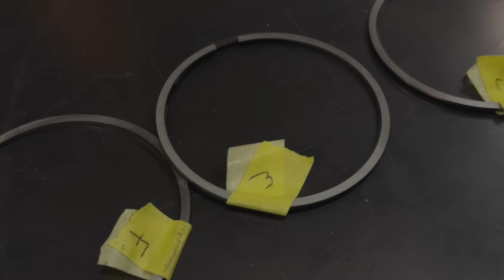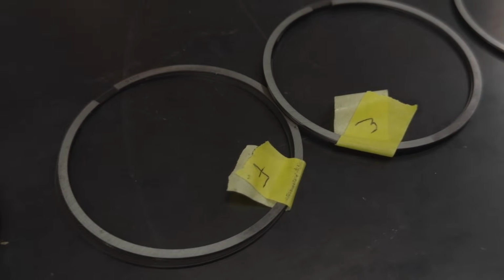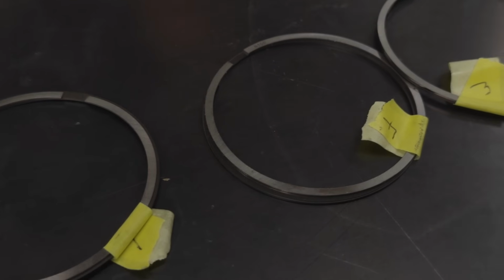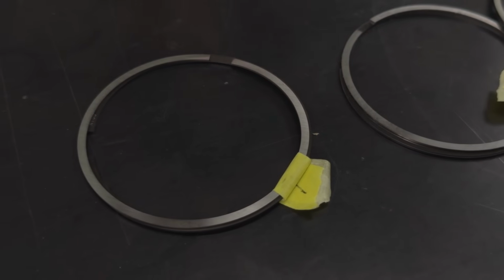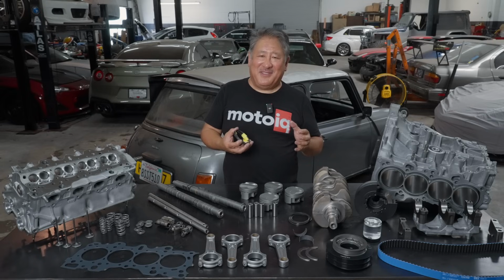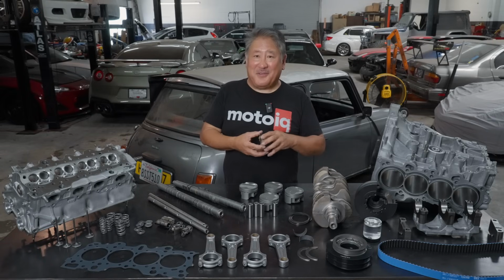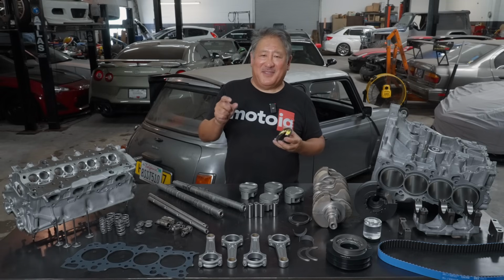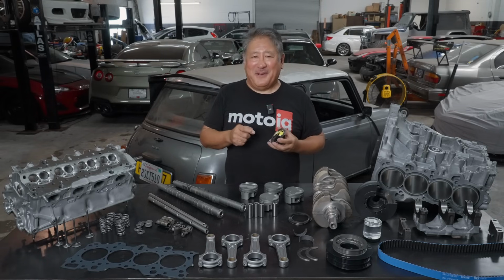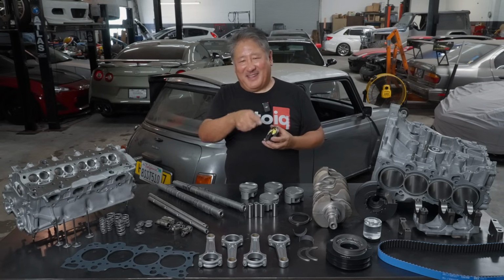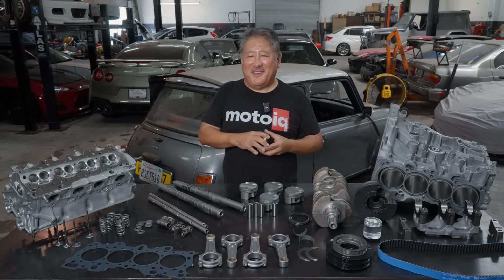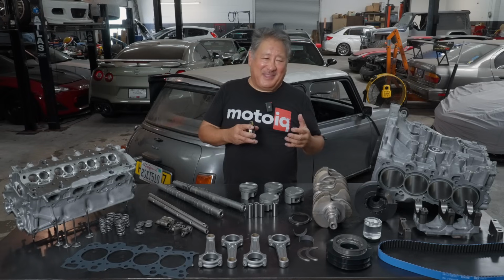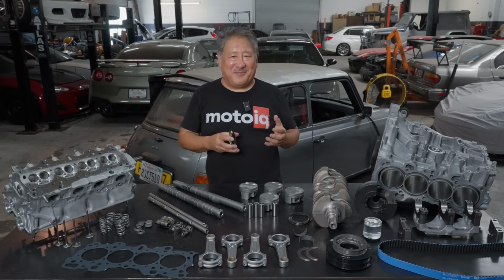Now the piston rings are JE standard rings, which I think are pretty cool rings. The #1 compression ring is really thin, really low tension. It's steel and it's nitrided. The nitriding gives a really hard, low friction, long wearing surface. The #2 ring is iron. It's also thin and low tension, and it has a Napier profile. A Napier profile means it has kind of like a hook at the bottom of the ring. Now the hook helps seal. The #2 ring receives less pressure than the #1 ring, and when you have a little thinner hook, you get a better sealing load against the cylinder wall with less pressure.